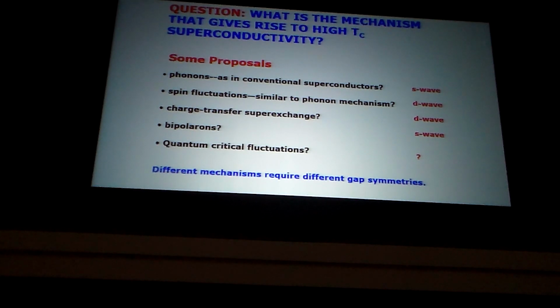Okay, so it's likely that there's some kind of magnetic interaction that's causing the superconductivity, which means it's a Coulomb interaction of some kind. Somehow the Coulomb interaction, which we think of as being very repulsive, can, in some situations, be actually attractive. And this has been actually known for, I think, since the 60s, even before I was getting my PhD, but I certainly didn't know about it. As far as I was concerned, all superconductors have S-wave symmetry. So it was a big surprise to me when these other symmetries came up.